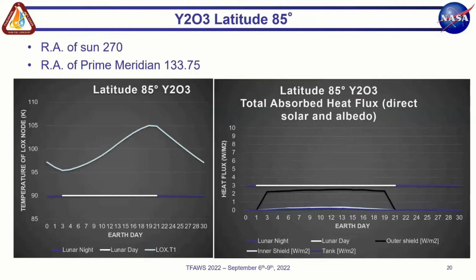And then when you compare the equator to one closer to the pole, you get even lower temperatures. That suggests these passive cryogenic missions are really latitude dependent as well. So your spacecraft geometry, your latitude, what solar coating you're using, and other factors too. Like we didn't look at MLI in these models. So there's a lot of important factors, and these are a few of them that we're pointing out here.